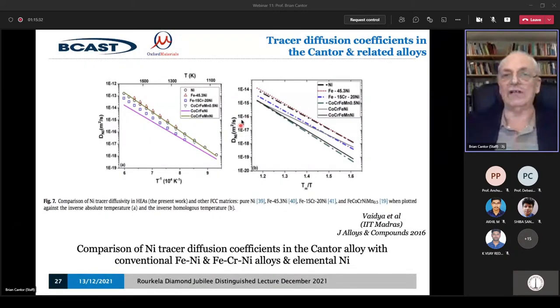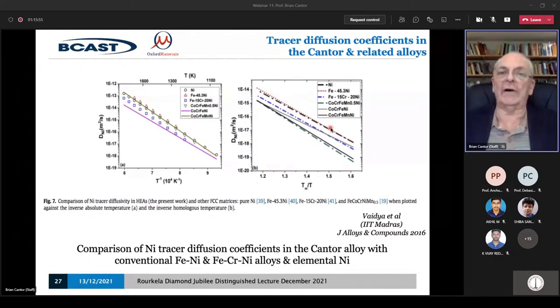It's usually linear here. This is for the Cantor alloy itself, two different Cantor alloys, these bottom two lines. And this is for pure face-centered cubic nickel, and one or two binary alloys which are face-centered cubic. And the difference here is about an order of magnitude. So the speed at which atoms move around is about an order of magnitude slower at all different temperatures.